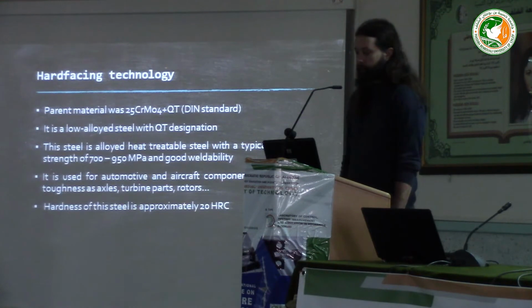The parent material used for the tooth was 25CrMo4 QT steel, according to DIN standard. The QT designation stands for the fact that it was delivered in a quenched and tempered state. It is a low-alloyed, heat-treatable steel with good weldability, and its tensile strength typically ranges between 700 and 950 megapascals. Such materials are usually used in automotive and aircraft industry for components which require high toughness, such as axles, axle journals, turbine parts, rotors, etc. This steel typically has a hardness of around 20 HRC, which, as you can notice, is significantly lower than the hardness of the welded material.